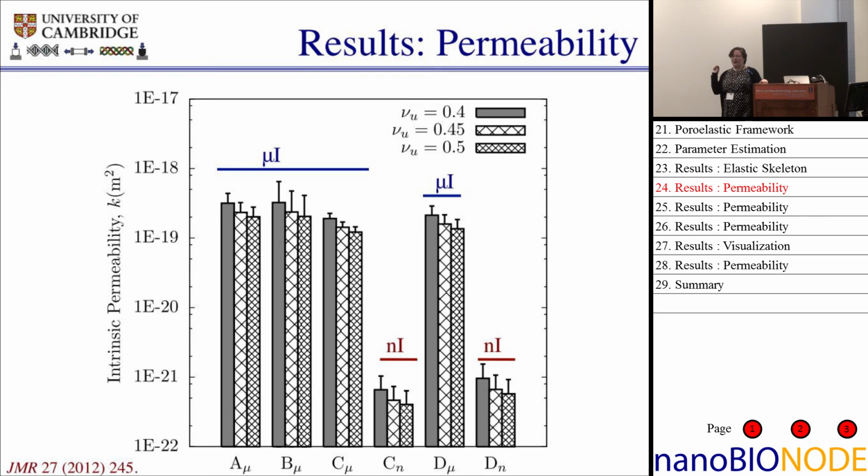So this is interesting. As we go to larger scales, it's easier for the fluid to flow. We go to smaller scales, and it's much, much harder for the fluid to flow. It's not like this is an ambiguous difference at 2.5 orders of magnitude. And this is fundamentally interesting and tells us something about our microstructure.